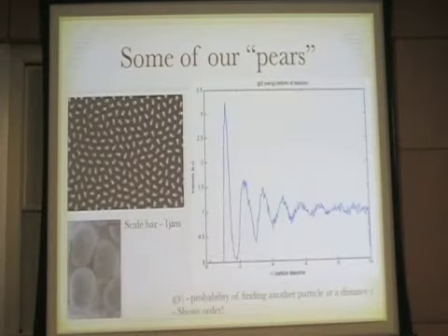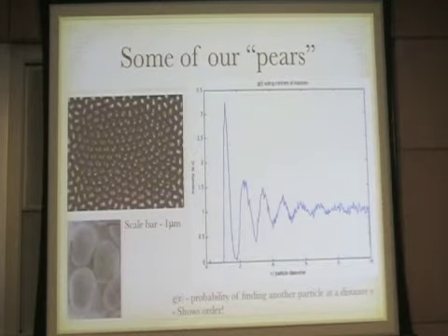So let's take a look at this picture. Here's the SEM of the particles that we have. This is a g(r) plot, the pair correlation function. The peaks show that there is certain long-range order in this system, so we are talking about a crystal. It's not just any random picture. In this plot, we track each particle, and if it's surrounded by 6 nearest neighbors, we call it black. So there is some sort of hexagonal or 6-fold symmetry here.